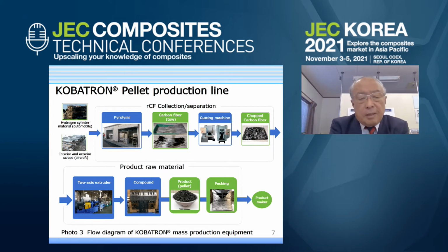And also, please see, normal recycling methods require chopped material, partly destroyed by some blocks, but we can obtain long fiber material like this. And this long fiber material is put into the cutting machine. It is a guillotine cutter, for wide materials or very small materials, and we obtain chopped fiber like this. And this chopped fiber is directly put into the twin screw extruder.